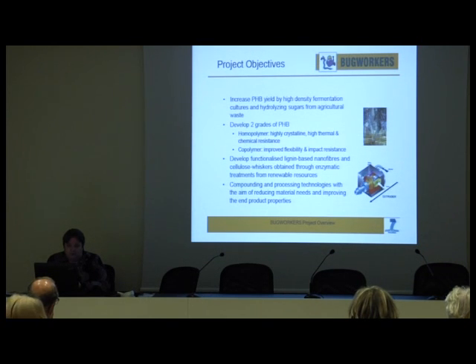We will produce two grades of PHB: a homopolymer with high crystallinity and high thermal and chemical resistance, and a copolymer with improved flexibility and impact resistance. At the end of the project, the idea is to obtain blends of these two grades in order to fit the properties of the different end-use applications. On the other side, we will develop functionalized lignin-based nanofibers and cellulose whiskers obtained through enzymatic treatments from renewable resources. And, of course, the compounding and processing technologies will be focused on reducing the material degradation and improving the end product properties.